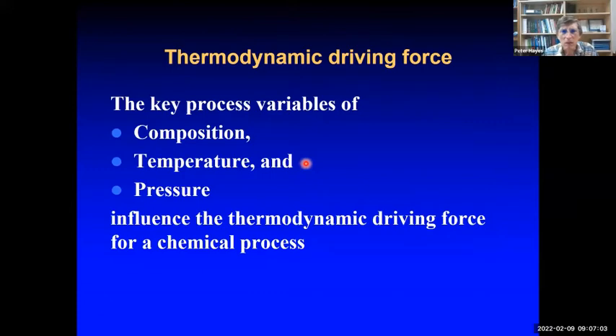So I want to start by taking those key process variables, the three of them, composition, temperature, and pressure, and realizing the first thing to come to mind is that it influences the thermodynamic driving force for chemical processes and chemical changes. So when we're examining different processes, we have to appreciate how close we are to the equilibrium to start with before we can then link that to how fast we might expect it to go. The two are not independent of each other. So we need to understand the driving force.